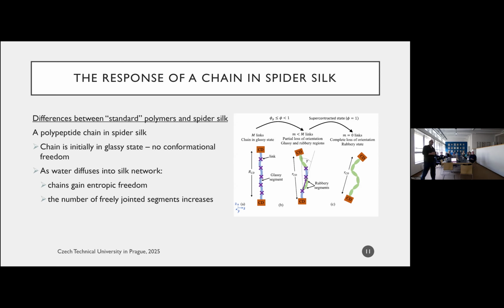And so silk fibers, if I want to take this and find the analog, silk fibers have a different microstructure inherently. So they start out in a glassy state. I'm saying glassy in the sense that the chain itself has no conformational freedom. Chains start out as a polypeptide segment that has pretty much no conformational freedom. It can't move around and maximize entropy. It's fixed. When water diffuses into the network, all of a sudden the chain starts to gain mobility, right? It starts to get these freely jointed segments along the chain that can occupy different conformations. And so the chain can start moving around, and then ultimately, when enough water has diffused into the network, I end up with just a random coil, or something that resembles a random coil.